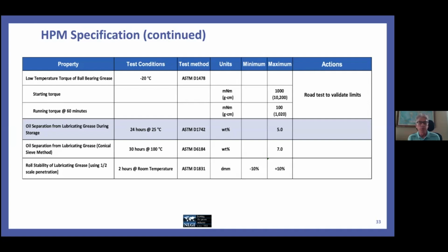Now we have roll stability as the last test on this slide. And again, this is another structural stability test, which we do not have in GCLB today. This is actually one that we came to fairly quick agreement on as well. The standard roll stability test, 2 hours at room temperature with a plus or minus 10% limit, seemed to be very agreeable to everyone on both the steering committee and in the interview process as well.